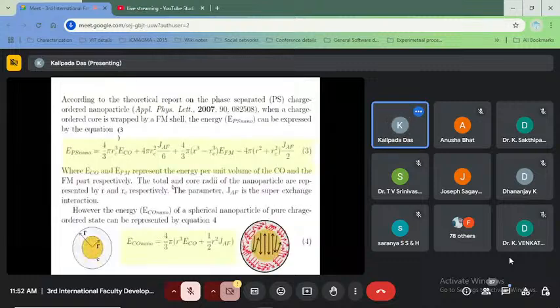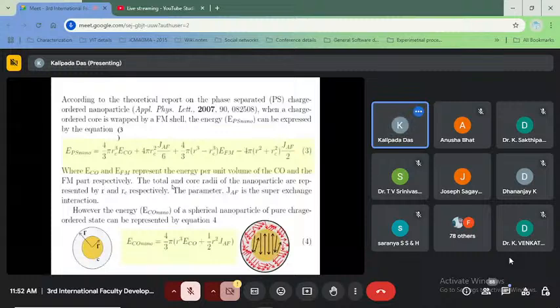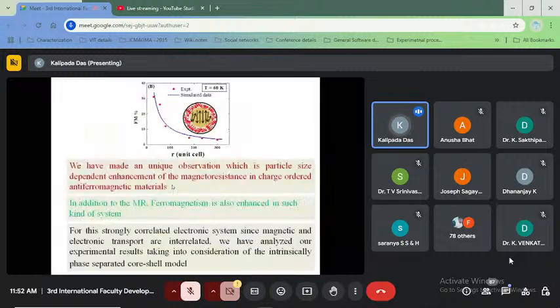According to their calculation, we can classify an antiferromagnetic nanomaterial into two different regions. One is the core, another is the shell part. In the core part, antiferromagnetic ordering is still there, but in the shell part, some short-range ferromagnetic correlation is newly developed. And due to this developed short-range ferromagnetic correlation, the magnetoresistance and magnetocaloric property get enhanced. According to their calculation, we have also simulated the ferromagnetic volume fraction with respect to particle size reduction, and we compared it with our experimental data, and it nicely matched.